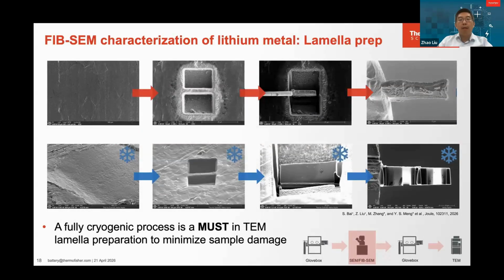However, if you want to do lithium metal lamella preparation, the situation changes. On the top, it shows the process of preparing lithium metal with a plasma FIB, but at room temperature. As you can see on the top right, the lamella ends up severely damaged. That is because once the sample gets smaller and smaller, the thermal conductivity gets worse. Your sample can no longer survive and handle the heat, causing damage. So to validate the process, we did the full cryo process for lamella preparation, which is shown at the bottom. In this case, the sample is well protected, and you can get a high quality lamella if you go through the full cryogenic process during lamella preparation inside the FIB-SEM.